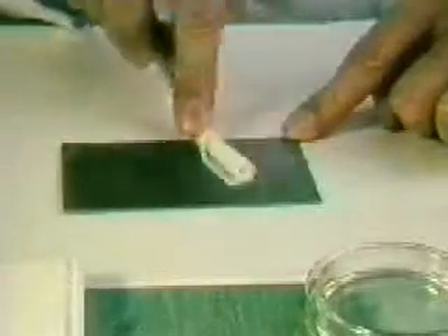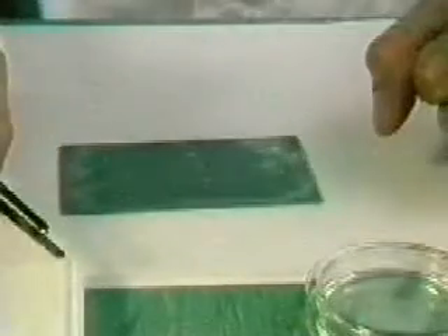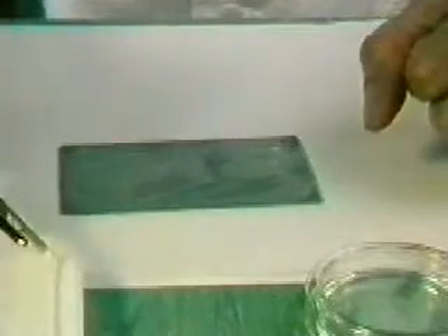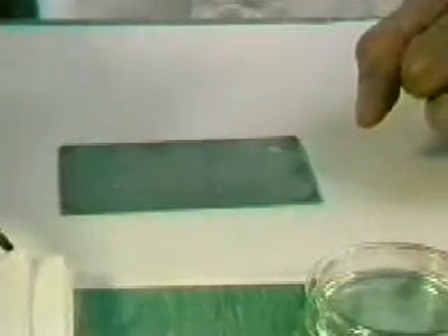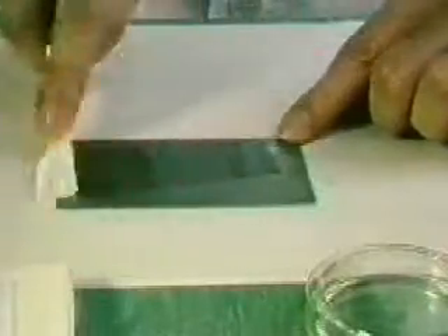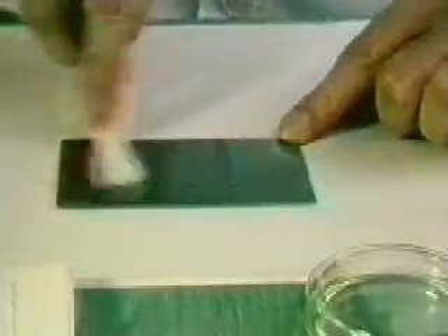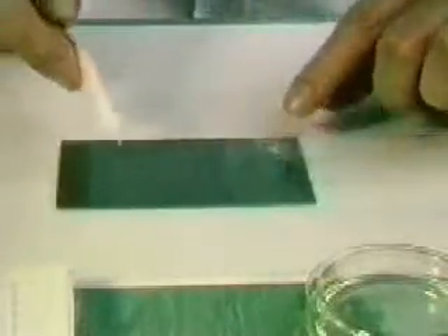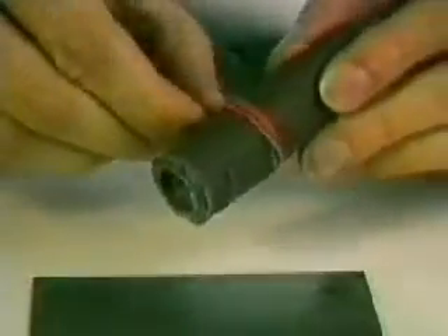Cleaning should not be restricted to too small an area around the bonding point. It must wash away all particles of dirt and grease from the mounting area. Any strain gauge cement needs a certain surface roughness to achieve the maximum bonding strength. For this reason, and also to remove layers of oxide that are always present on bare metal surfaces, the next stage is the roughening of the surface.